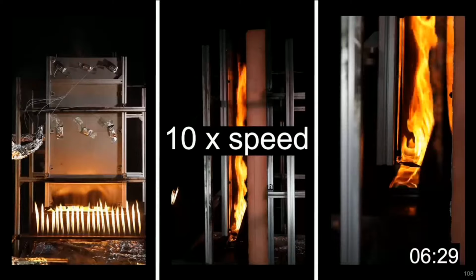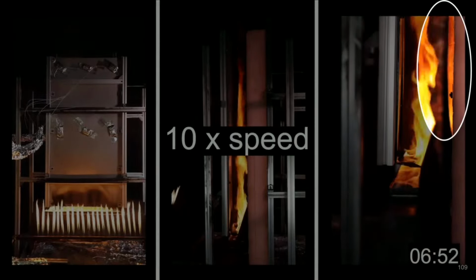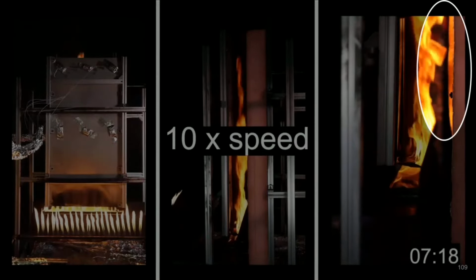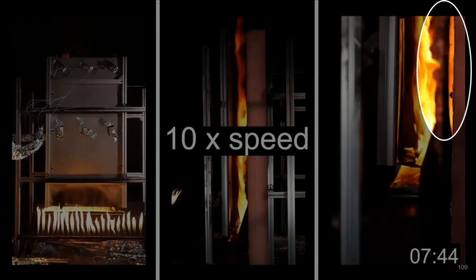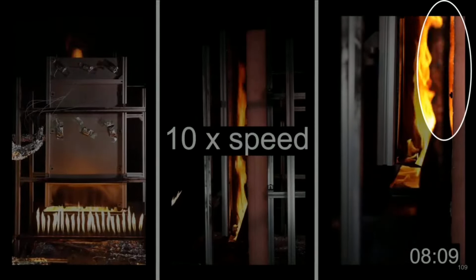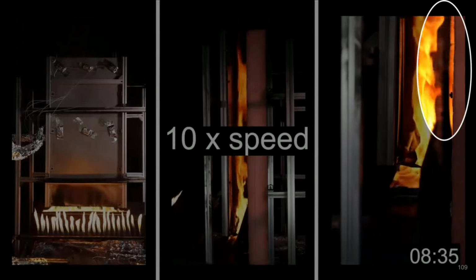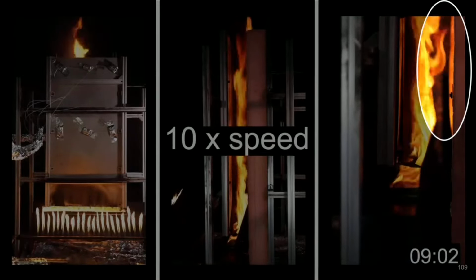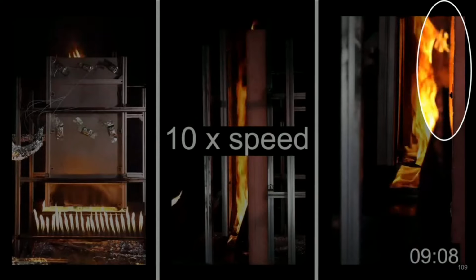At 9 minutes and 9 seconds, if you watch the highlighted area at the top of this slide that I'll show you in a moment, you'll see that flaming becomes visible on the surface of the foil-faced K15 insulation. So if you watch that highlighted circle, near the end of this clip, you'll see some flaming of the insulation. It's a bit clearer in a moment. The flaming then continues at this location, albeit only briefly.